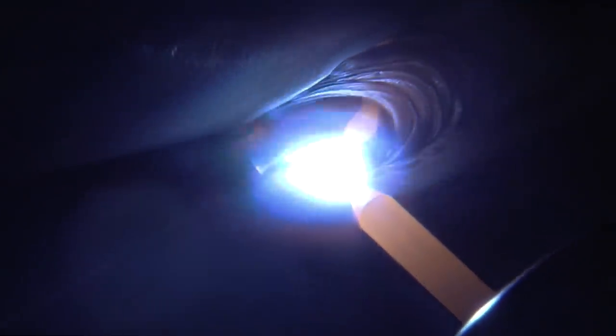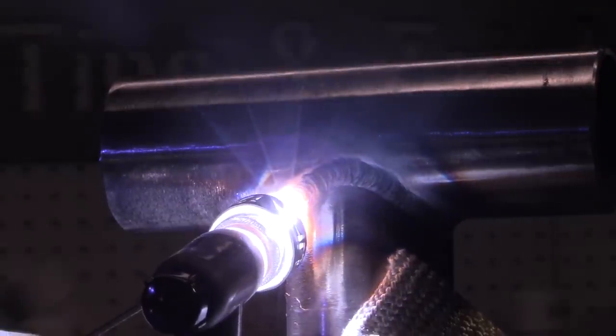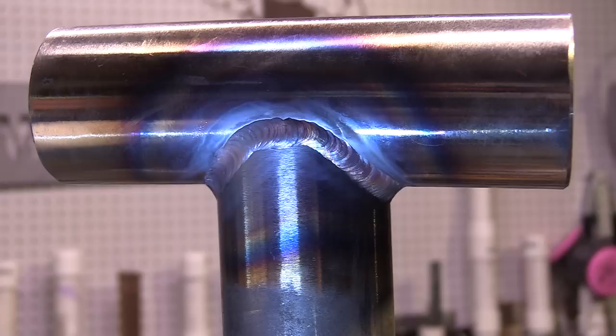Not horrible results. As long as the first pass is clean and pretty much free from oxidation goes in good. If you got a really gray oxidized weld it won't go in so good or you need to really power brush it before that second pass.